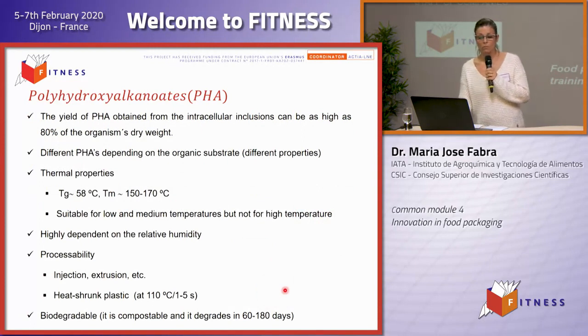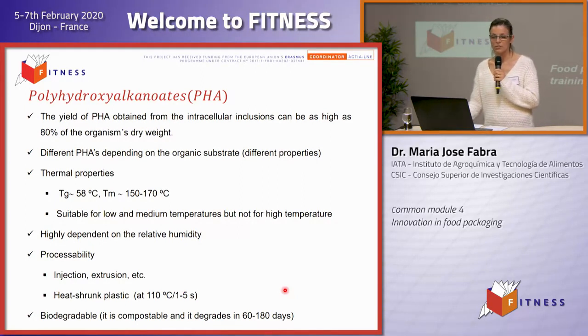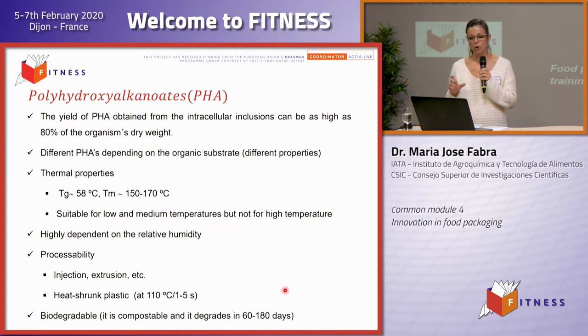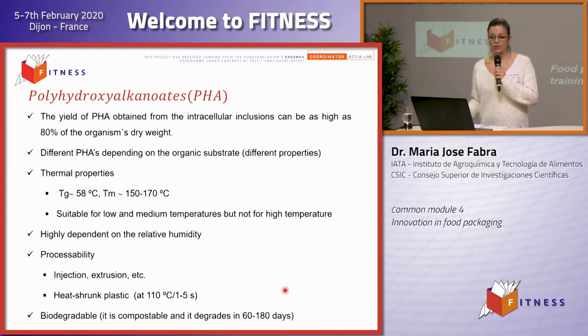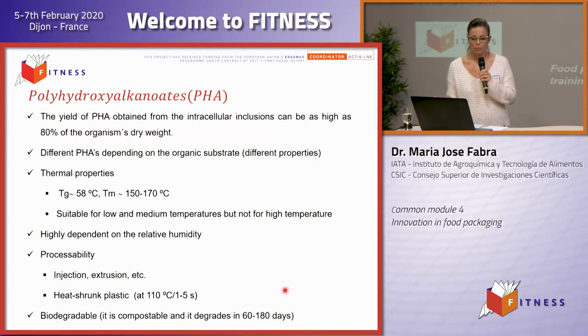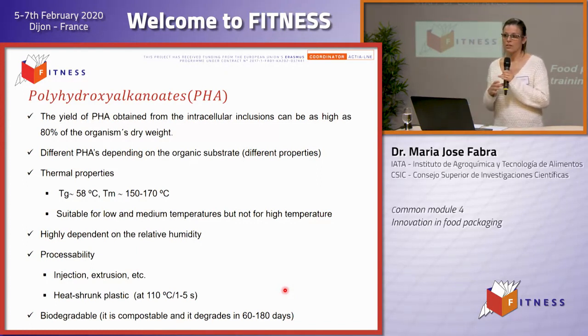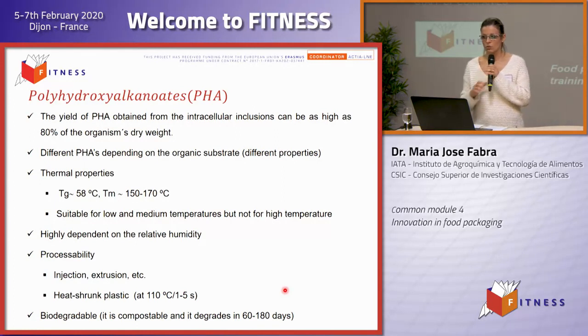The yield of PHA obtained from the intracellular inclusions can be as high as 80% of the organism's dry weight, and we can obtain different types of PHA with different properties depending on the organic substrate. We can obtain PHBV, which is a copolymer of polyhydroxybutyrate. This biopolymer is highly dependent on the relative humidity, which is one of the main drawbacks of biopolymers, and it can be processed by conventional equipment such as injection or extrusion. Furthermore, it is biodegradable and compostable, and it degrades between 60 and 180 days.